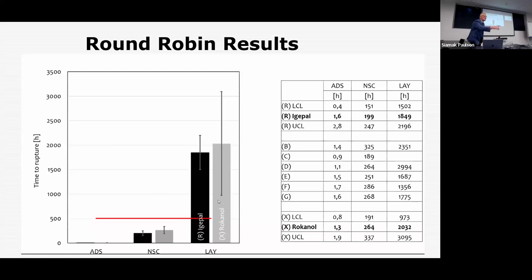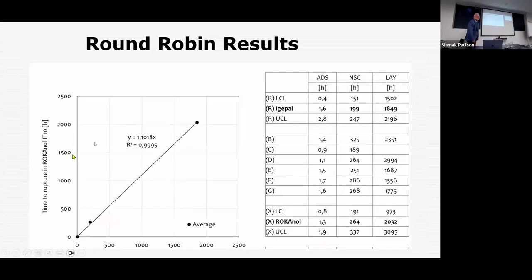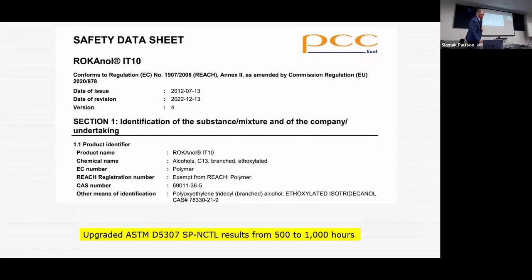Oh, Graham, you're never impressed. So I take it this is shown in a different way, but look at that R squared. It's almost too good to be true. I even see Warren smiling in the back, but this is a very nice set of circumstances. And I congratulate the Europeans very much for doing it. It's available through PCC, and I'm in charge of ASTM D35. So the single point notch constant tension load will switch to this surfactant next month.